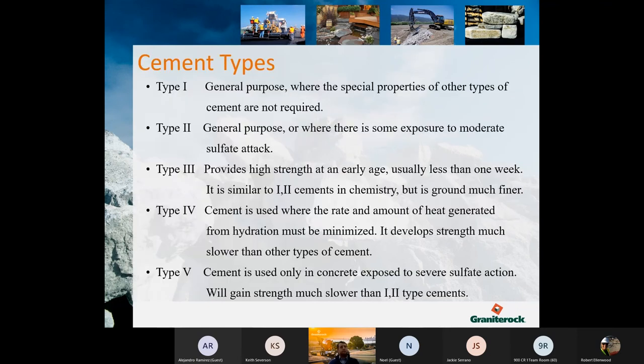To run over the different types of cements, one through five, type one is general purpose. Type two is general purpose as well, but has different admixtures in the cement to help deal with a sulfate attack. Type three is similar to type one and two, but it's ground finer. And when the cement is ground finer, it reacts quicker to the water just because the particles are smaller. And this helps when you need a higher strength concrete.